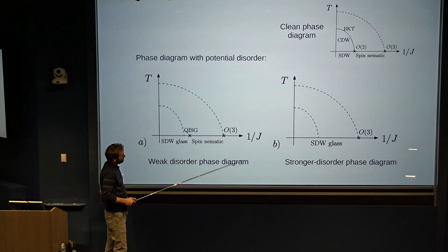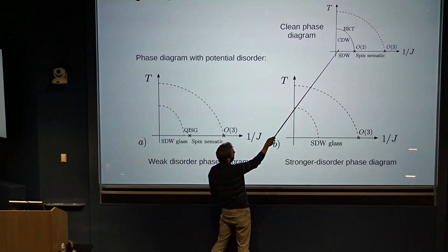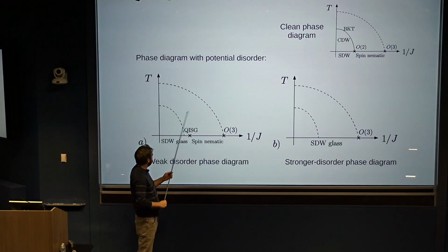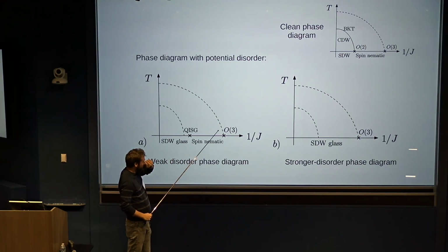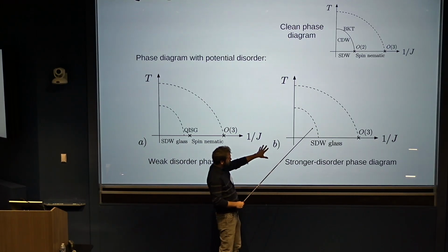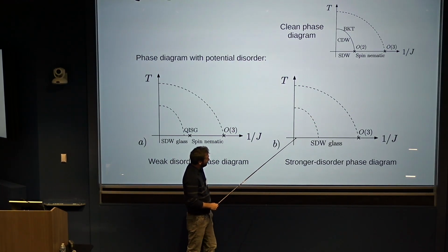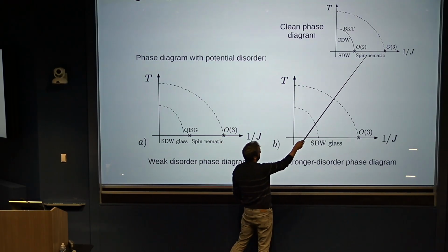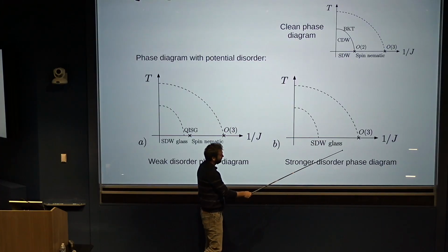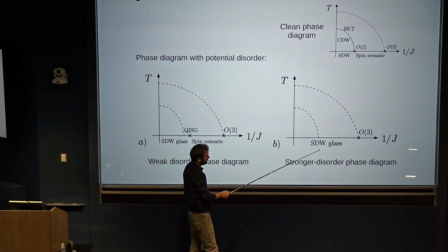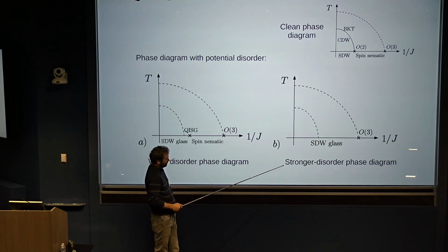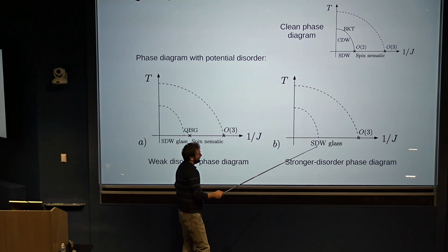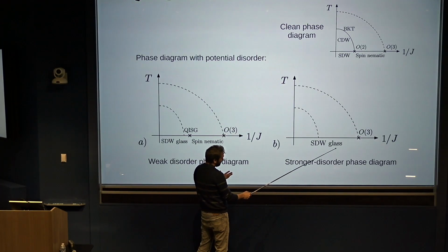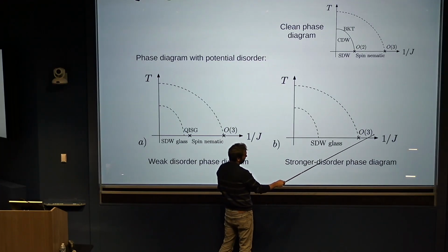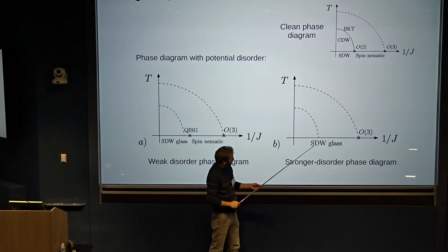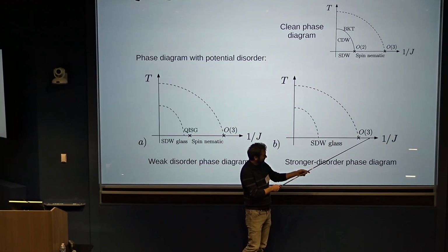Okay, and so this is then the phase diagram you have with disorder. Here for reference on the top right is again the clean phase diagram. Let me ignore the left possibility. This is what happens with weaker disorder, but that's not important for the rest of my story. Let's just focus on this phase diagram here. It seemingly becomes a lot simpler, because now the spin nematic becomes what is called the spin density wave glass. This is this Ising glassy order now, with this random charge configuration with a frustrated spin order pinned to it. And then there's a single O3 transition that remains from the pure model that separates the spin density wave glass from a state where the magnetism is gone.